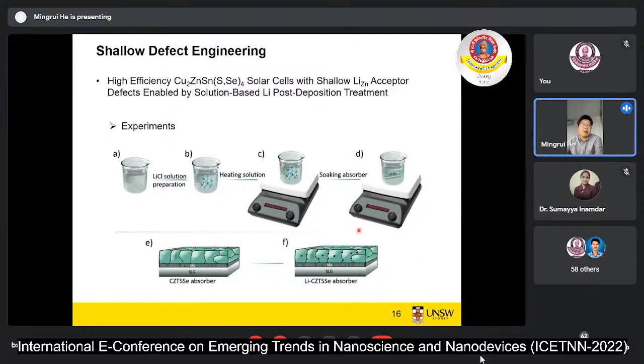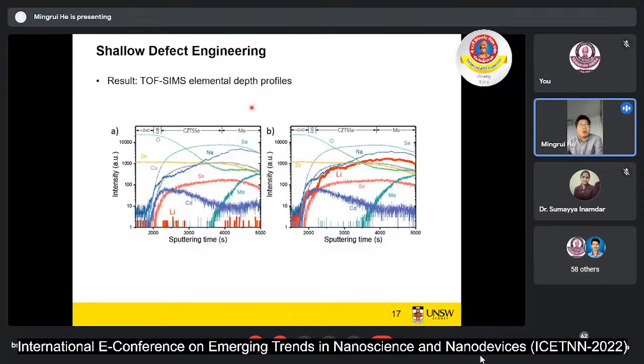Once I dope the lithium, the lithium will go into the bulk, and some will go to the grain boundary of the CZTS. First, I check the ToF-SIMS, which is one of the characterizations that tells us where the elements are located. As we can see, the left one is the reference and the right one is the one with lithium doping. Obviously, we can see a strong signal of lithium on the right, and on the left side we can almost not observe lithium.